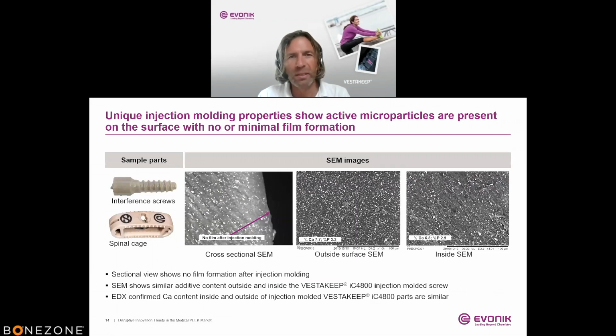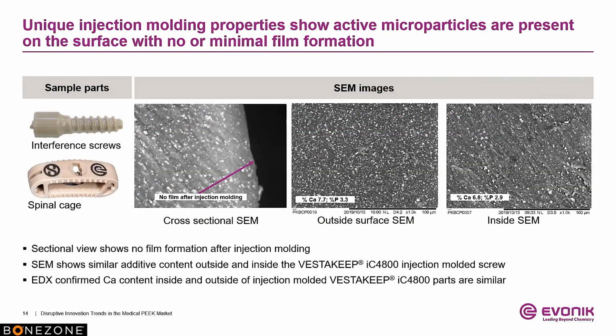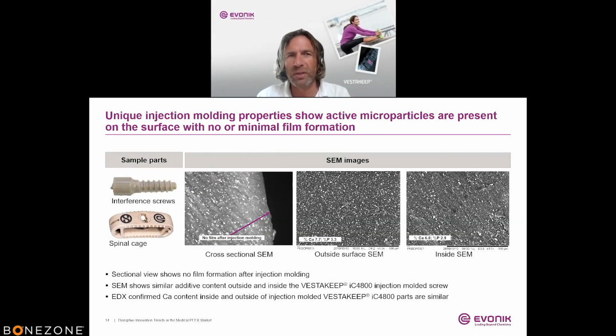So as you can see here, for example, we made some SEM images, and we compared the images from outside and with also some inside images, and there you see actually perfect distribution of the particles, and you see the calcium on the surface, and so very homogeneous, very small particles, and no film formation. That was something we wanted to show, and we were very satisfied with these pictures.